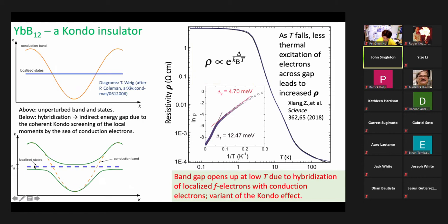So now the Fermi energy will usually be pinned to this set of localized states. So there's no mobile states at the Fermi energy. The electrons are all in here, and there are no electrons up here. So that's why the resistance tears off. It does a slightly strange thing at low temperature, which one of you can ask me a question about at the end.